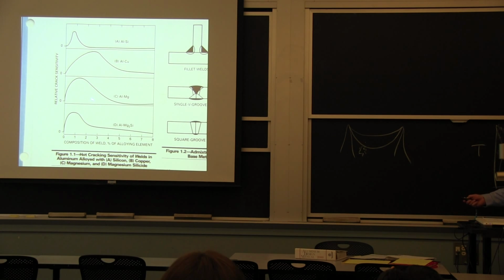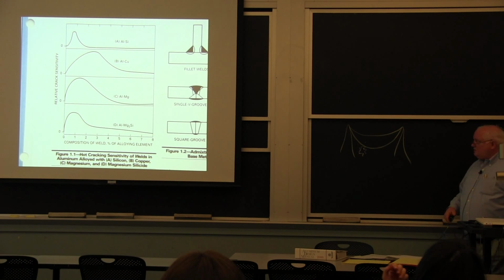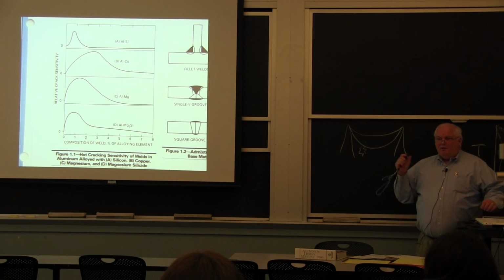The maximum in here is at 1 or 2%. This is the maximum. Relatively pure. Well, if it's pure aluminum, it melts at 1 temperature, right? If it doesn't have much alloy content, the delta T is small. You get up here towards the eutectic, and you see the crack sensitivity goes way down. So this is a plot of crack sensitivity. Where does it come from? It comes from the freezing range of the alloy. So you have to be careful, okay? I don't know if I want to teach you that metallurgy right now.